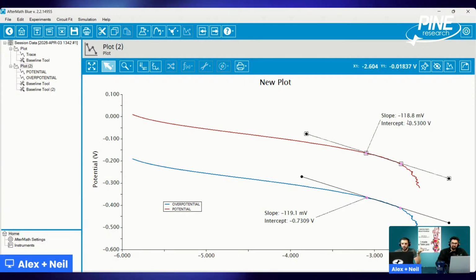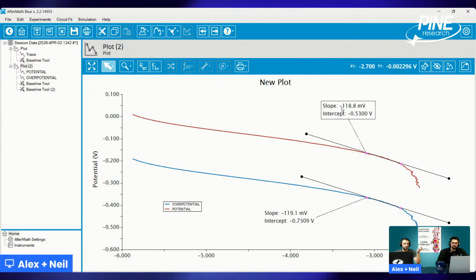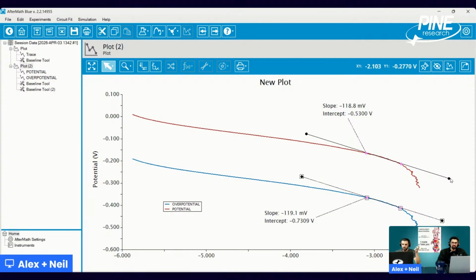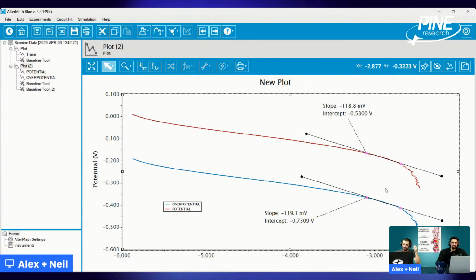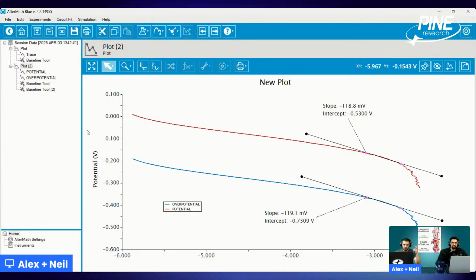And so to that point, which is part of your question, it doesn't matter what you plot specifically for the potential, overpotential or regular potential, because it's a slope. If we were looking at it properly, we would use overpotential based on the definition of the Butler-Volmer equation and the Tafel equation. But strictly speaking, for the calculation, it makes no difference. So if you're worried about, well, which potential did I use? Do not worry. It doesn't make any difference because the slope takes into account the change.